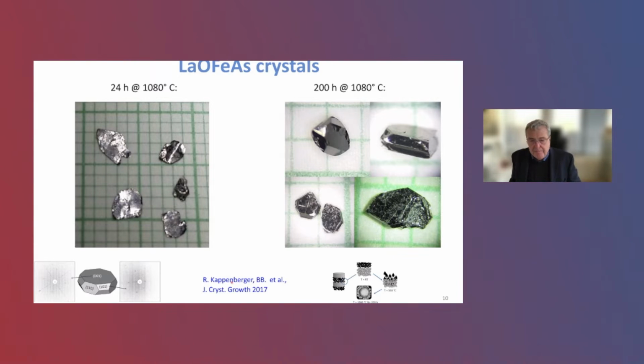That is Ria Kappenberger doing a PhD. She found a way to synthesize these really very nice and large single crystals. And that's a very unusual way. It's based on abnormal crystal growth. It's connected to polycrystalline material synthesis. And then you have to do very special thermal treatments, very special alignment of materials. And everything is described in detail in this Journal of Crystal Growth article. And then you finally end up with these very nice, faceted, large single crystals of this lanthanum oxygen iron arsenide. And that's the starting point of this additional initiative of us to revisit this system.